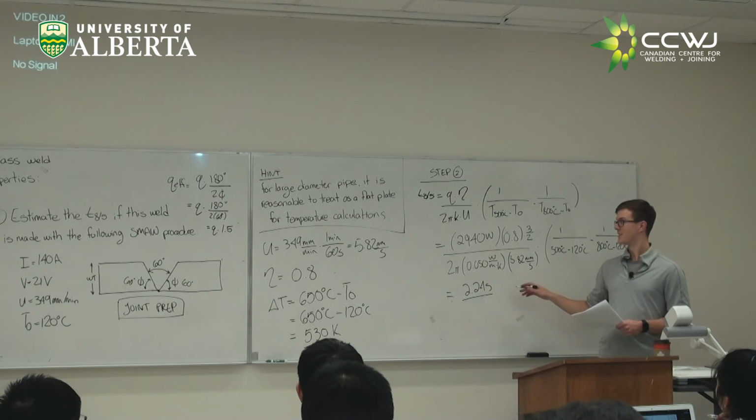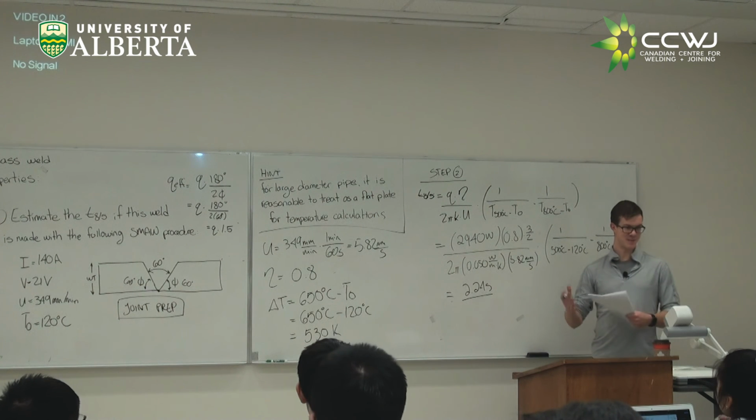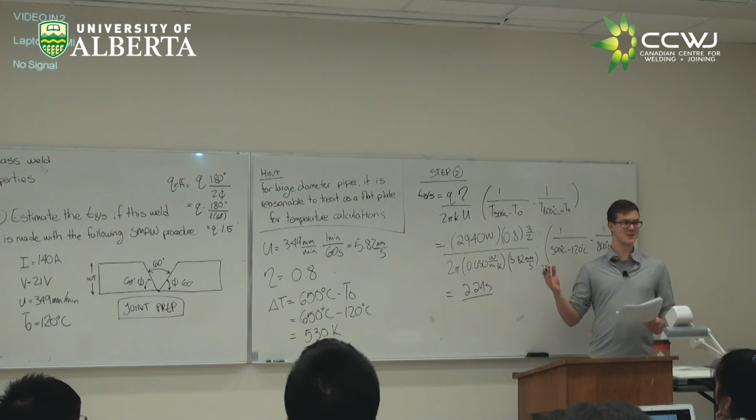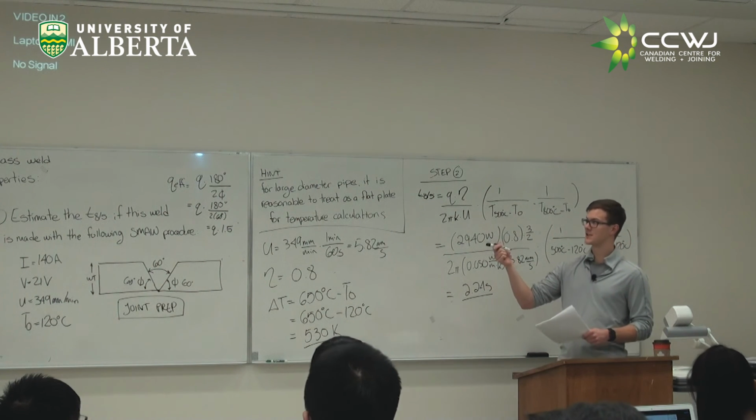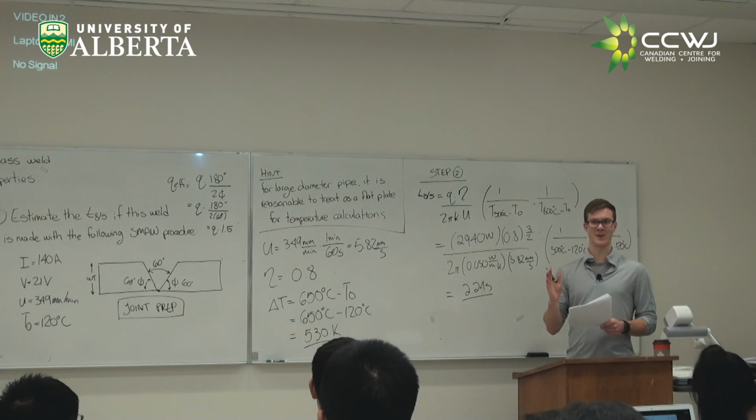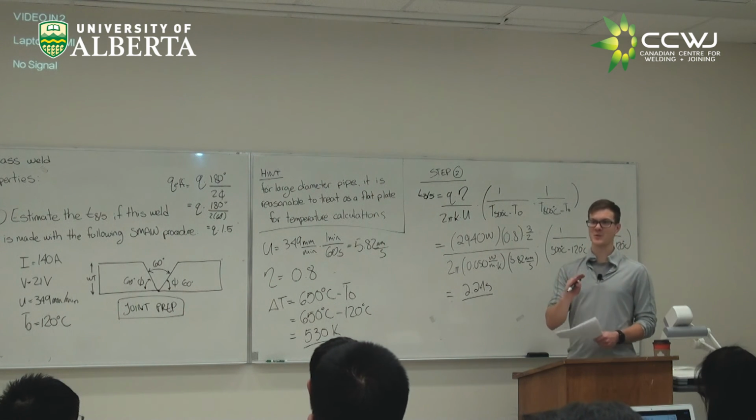No. If we're in the thick regime, it doesn't matter how thick we are. If you make it thicker, we're still thick. And if you look at your process map, all changing that thickness would make our D star larger, and we'd actually become further away from that line, more into the very definitively thick regime.